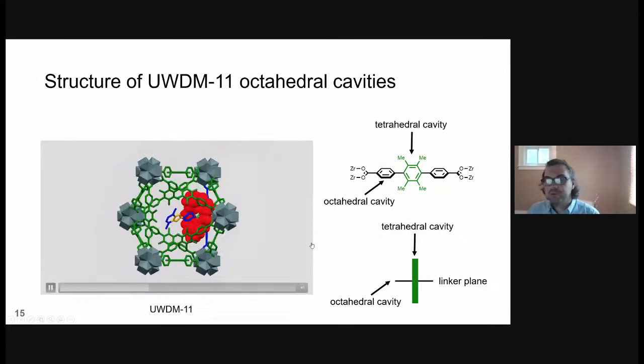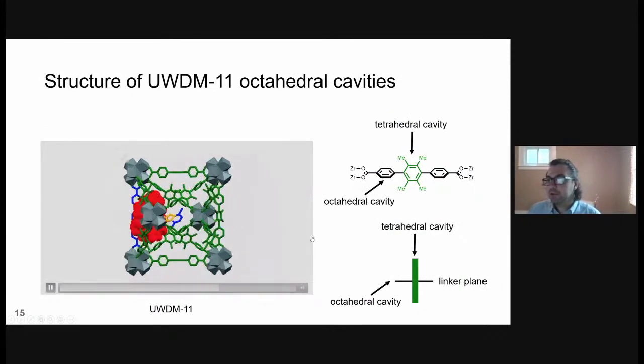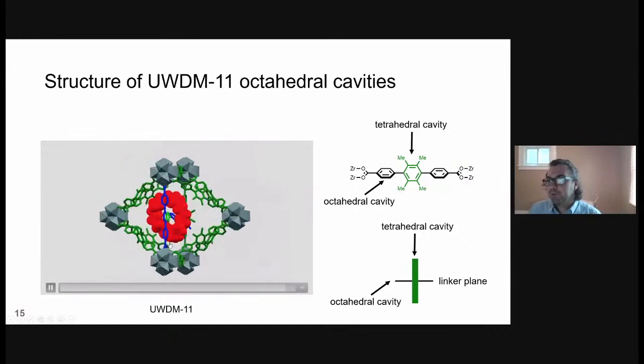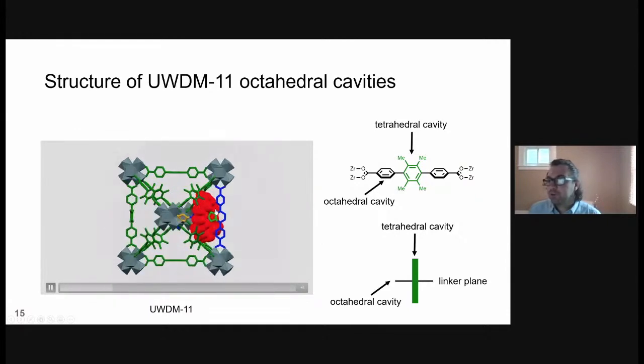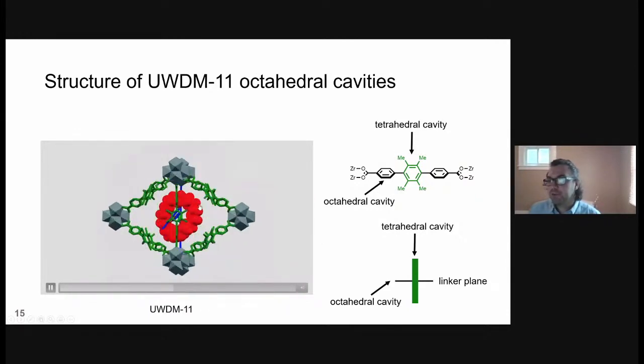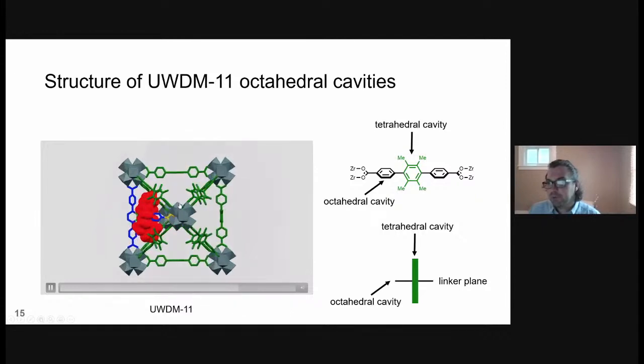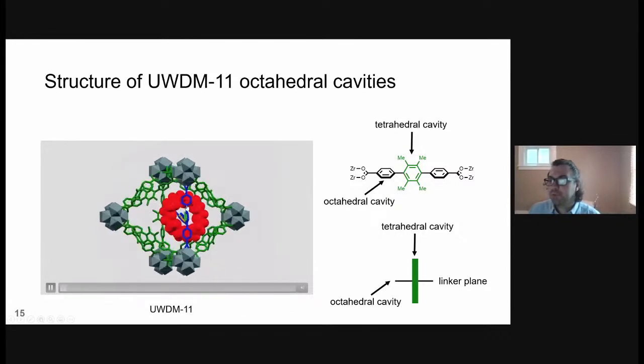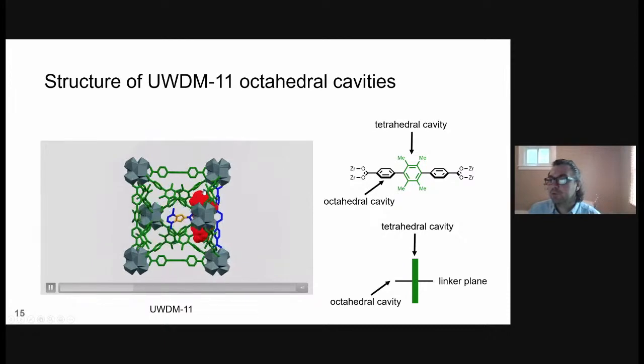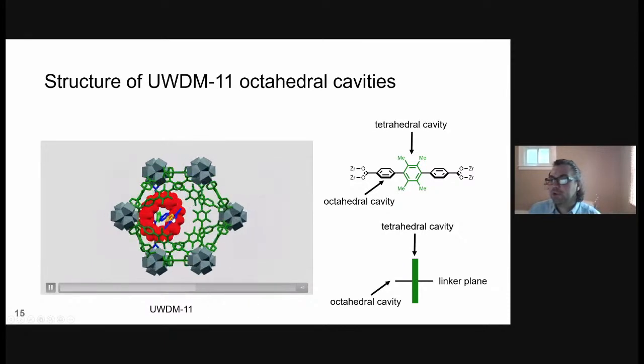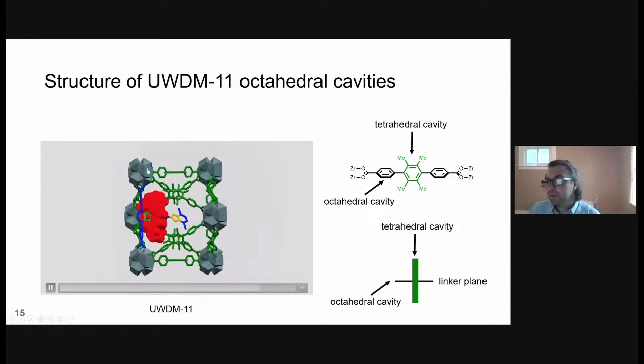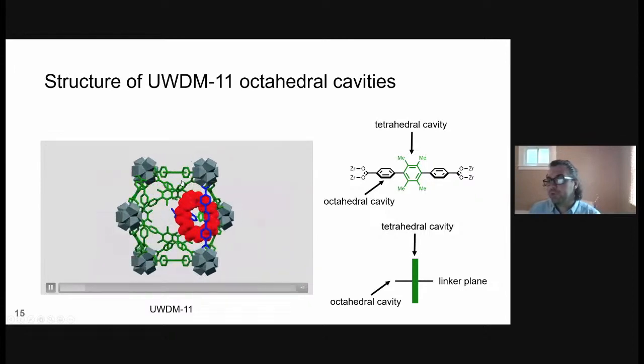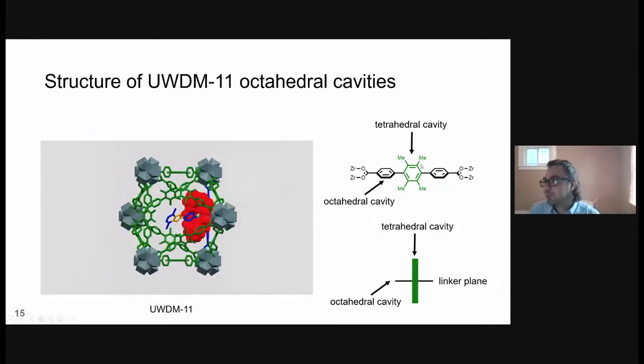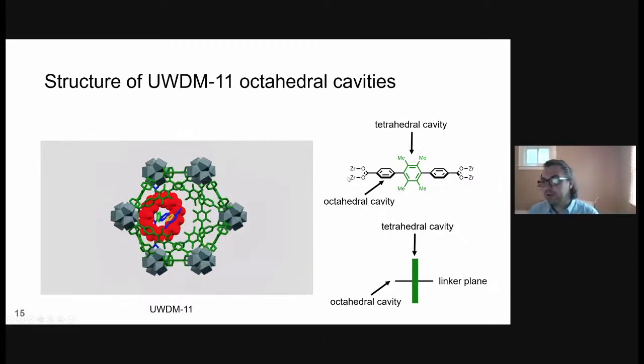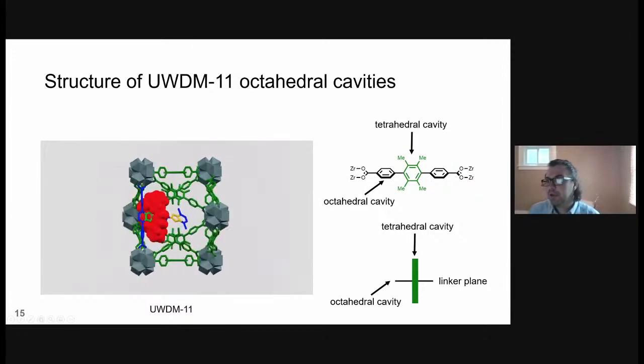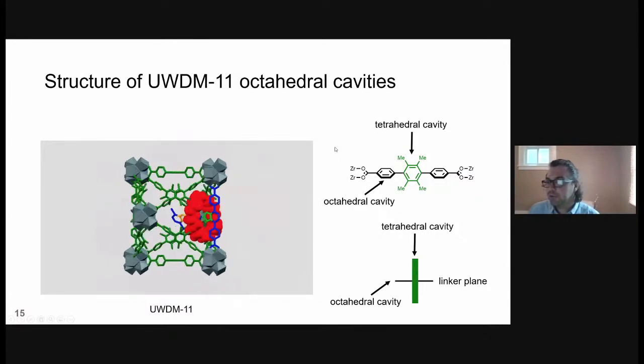So in terms of what this octahedral cavity actually looks like, we have this appended rotaxane on one edge of the octahedron, and we can see there's plenty of vacant space, when we have the activated MOF, for this ring to move from this recognition site to this one. Of course, as we're in the octahedral cavity, these methyl groups are pointing into the tetrahedral cavity, so they're not going to have any steric blocking effects that we saw in UWDM8.